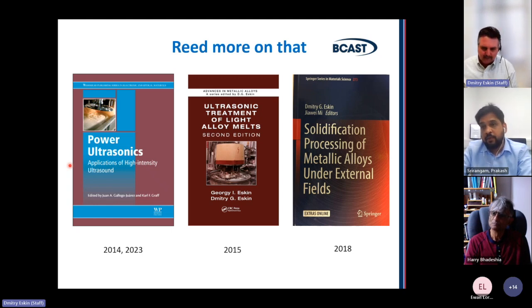But you can do it indirectly. There are two ways of doing this indirectly. One is not efficient, in my view, but people tried it: to introduce it through the mold. If you cast, for example, continuous casting of steel, and you have a mold, you can vibrate the walls of the mold, and through that transmit vibrations into the liquid metal, so indirectly. But this is a very inefficient way because you have huge losses of acoustic energy going through a tool, through the mold, and then to the melt. You have air gaps, and then you have interfaces. Each of them will reflect acoustic power back. So it is very inefficient. In small volumes, people demonstrated it's possible, but I don't think that it's possible on a large scale.